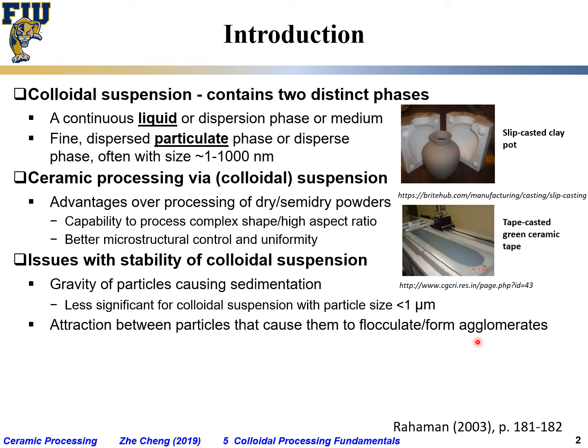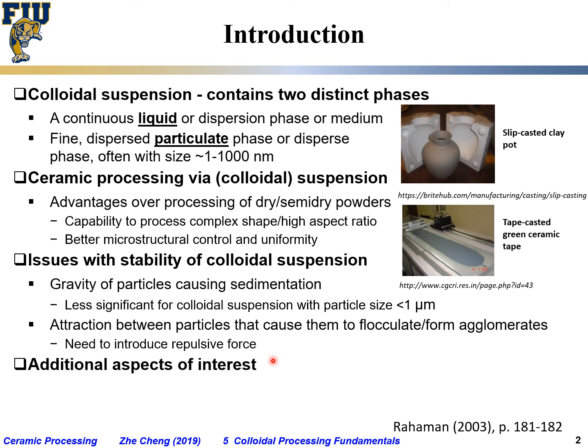Initially you have uniformly well dispersed single colloidal particles, but after a while you find quickly the particles, after sonication, you let it sit. If you do not add any additives, quite often they quickly attach to each other, and once they attach, they become heavier, relatively packed denser, and they drop to the bottom, causing sedimentation. So as a result, for colloidal suspension, we need to introduce repulsive force. And we will talk about how to introduce repulsive force.